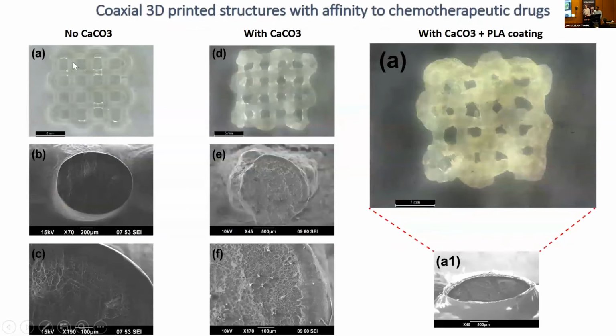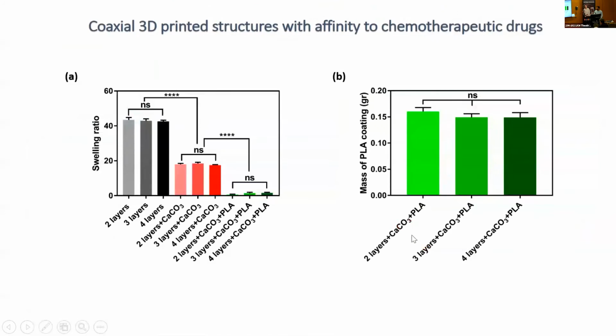Instead, what we've done was use an additional cross-linker, calcium carbonate. So these patches either didn't have calcium carbonate, or they had calcium carbonate, or after we made these patches with calcium carbonate, we subsequently coated them with PLA, which is a hydrophobic polymer, to further slow down the release of drugs. And then when we took the SEM images, you could see the effect of calcium carbonate in reducing the pore size diameter, and then eventually the PLA coating around these patches.